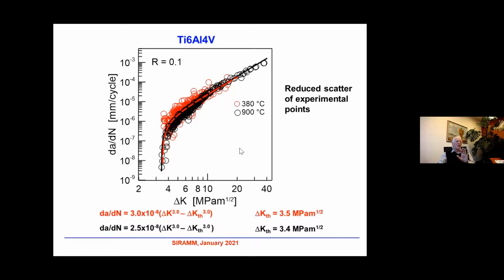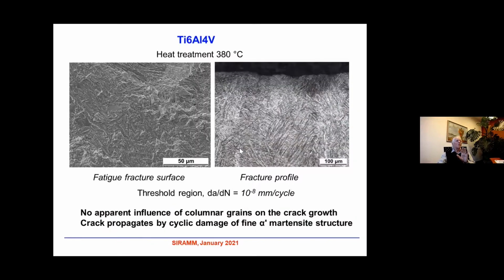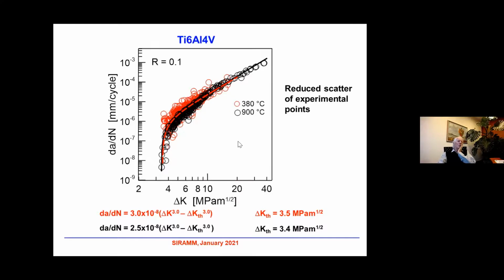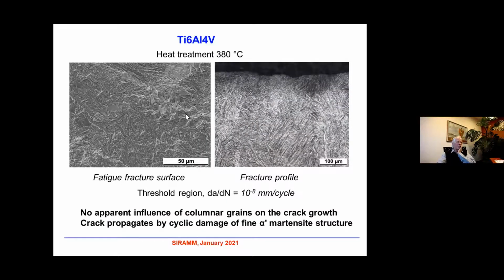Now I would like to show you the fracture surfaces. At 380, the fatigue crack propagates practically in the threshold region, so in the region where the crack growth is very slow, through the microstructure. So the crack profile is very flat, and the fracture surface doesn't exhibit special features. There is no apparent influence of columnar grains on the crack growth. The crack propagates in this case at 380 at this low rate by cyclic damage of fine alpha prime martensite structure.